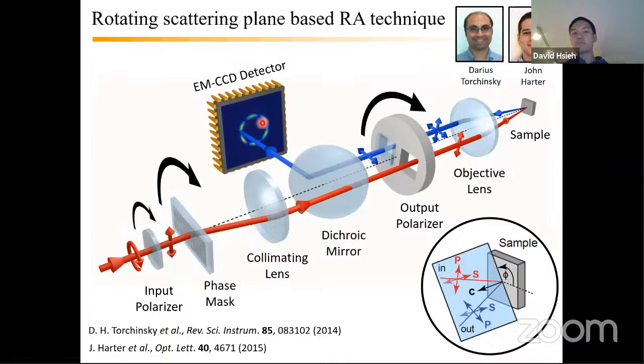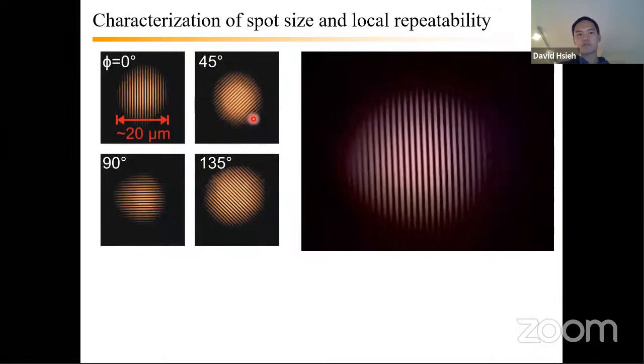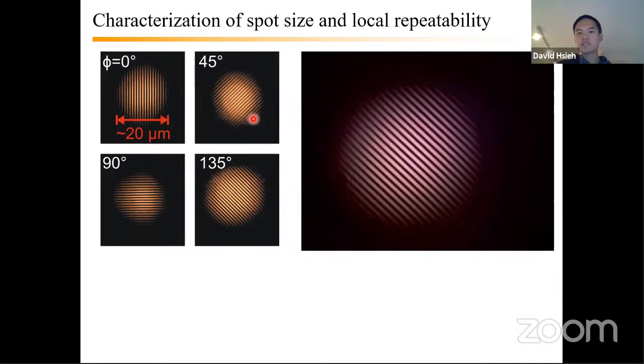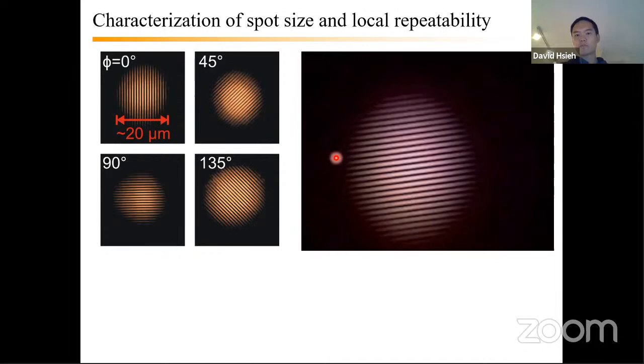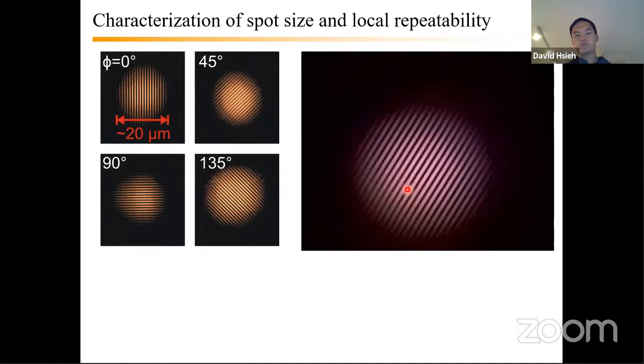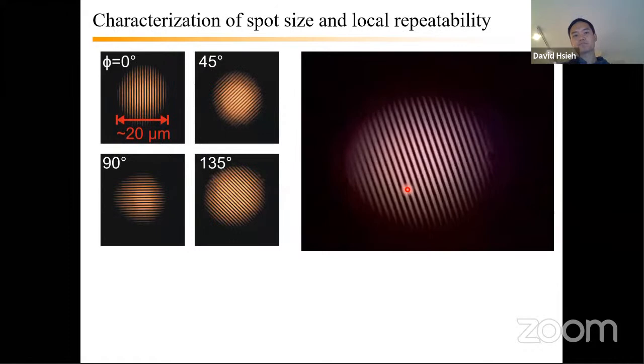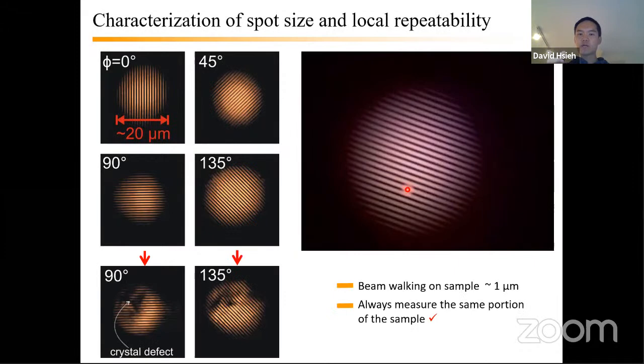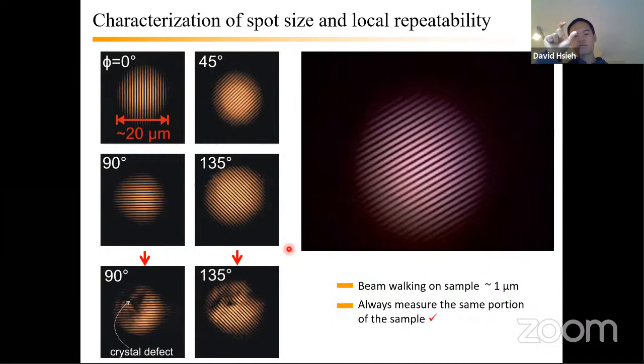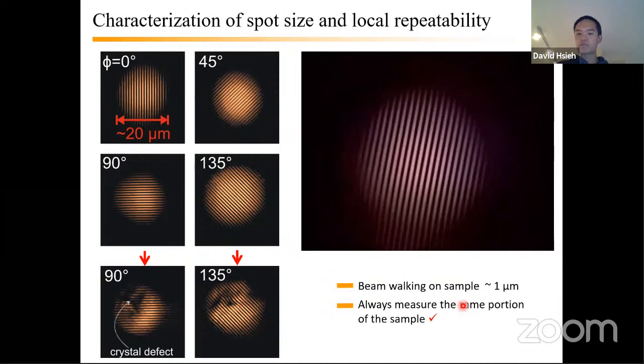So just a few characteristics on the performance of the setup. Again, I won't go through all these details. Here's a picture of two beams just coming in to the sample, forming an optical grating as a demonstration of how well our alignment can be done. And here you see that there's very little beam walking. Okay, we can quantify that by purposely looking for a defect and then quantifying how much we walk as we rotate the scattering plane. The walk is pretty good. It's limited to about a micron or so.